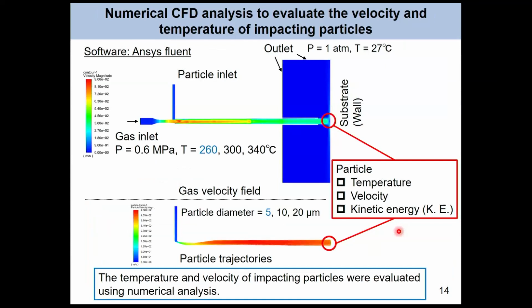To investigate the particle momentum, we performed a CFD simulation using the commercial software ANSYS Fluent. We set the cold spray dimensions, and we changed the inlet gas temperature from 260 to 300 and 340. We estimated the particle temperature, velocity, and kinetic energy in front of the substrate before impact. And the particle size also changes from 5 to 10 to 20.